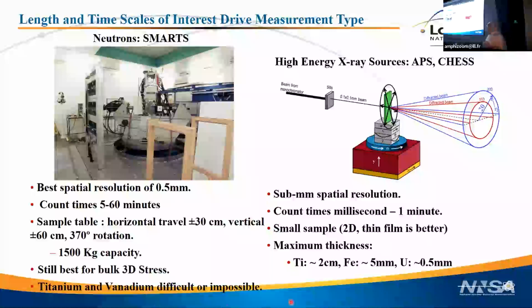But as you crank up the energy, you can start to go through quite thick parts and get three-dimensional stress fields, even in thick parts. Titanium, you can go through 2 centimeters. Iron, 5 millimeters, probably a bit further than that. And for the things that I care about, even uranium, and we've now even demonstrated plutonium, you can go through 0.5 millimeter of material with 100 keV X-rays and get bulk information in a way that you couldn't 10 or 15 years ago.